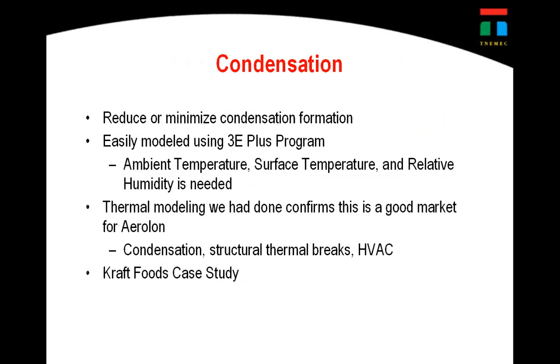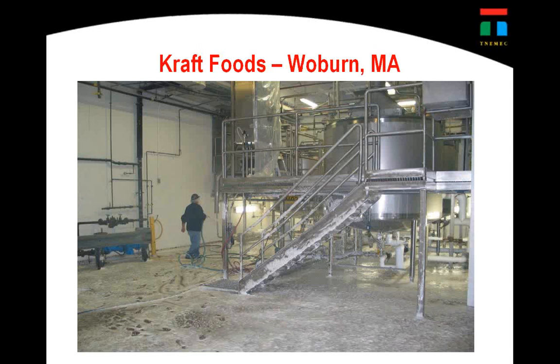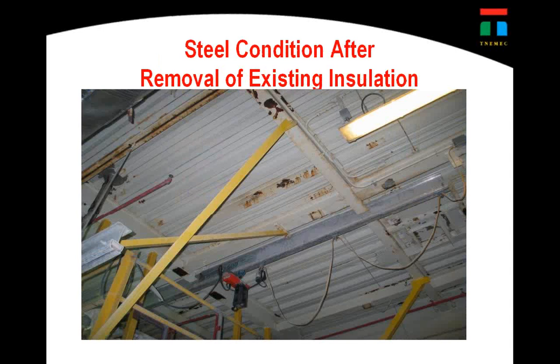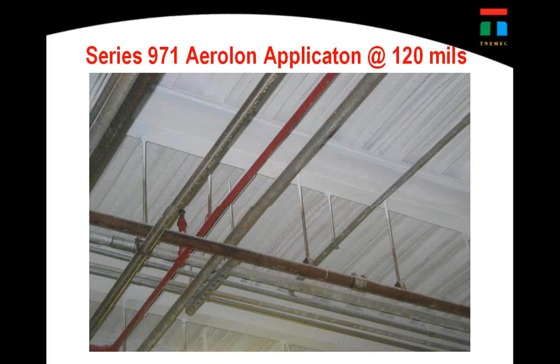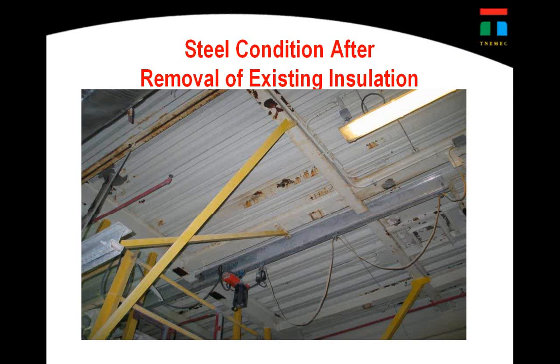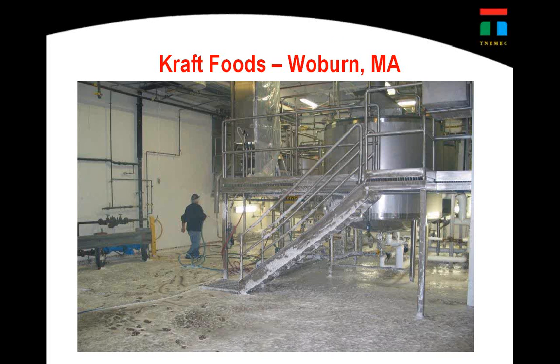Okay, so let's talk about condensation. One of the things that's interesting about this technology is that I'm going to jump forward a second so you can see this. What you're looking at is a job we did at Kraft Foods, right outside of Boston. What's interesting about this location is that there was foam insulation on the surface. All the foam insulation had basically disbonded, with air gaps underneath it, and started getting a lot of corrosion under insulation. So in this plant, you can see in this particular location, this room operates at about 82 degrees F on a regular basis. The room above it was operating at about 45 degrees.